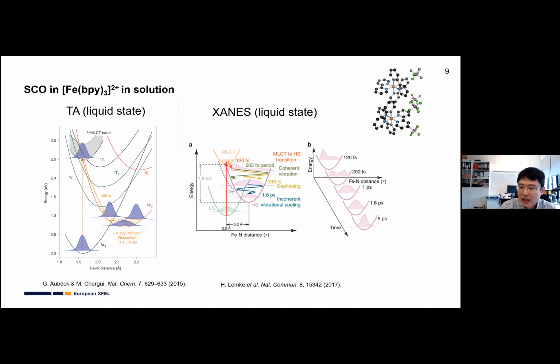But still, electronic state change has been studied very well, but the structure information is still not very clear. For example, by X-ray absorption near edge, they can study iron-nitrogen distance, because X-ray absorption near edge is sensitive to the target atom's distance to its closest atoms. So they can see oscillation of the iron-nitrogen bond distribution, and it's narrowing down in the high-spin energy surface. But what is the ligand's role and what is the ligand's response to this iron-nitrogen bond elongation is still unknown. So in order to study it, we must use diffraction.